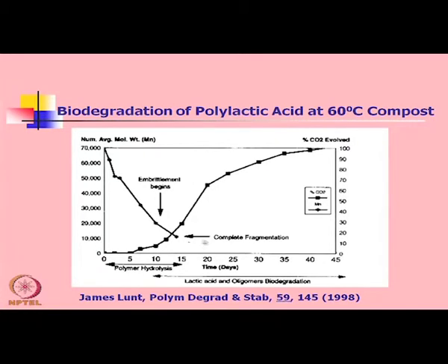was completely fragmented at 60 degrees Celsius temperature in compost condition, and you see the molecular weight has come down from 70,000 average molecular weight to almost 10,000 molecular weight fragments. And it shows almost complete biodegradation, 100% biodegradation in 40 to 45 days time period.